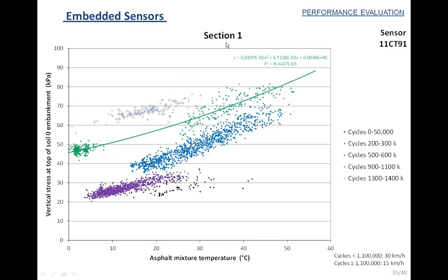So this is the reference section, this is section number 1, and you can see here that at the beginning of the test, these black points correspond to the beginning of the test. You have here the vertical stress, and you have here the asphalt temperature. Of course, you see that the stress is increasing with asphalt temperature, and during the test, the stress level kept increasing. So this is at the beginning of the test. This was after 200,000 cycles. These blue points correspond to 500,000 cycles. Then these green points correspond to 1 million cycles.